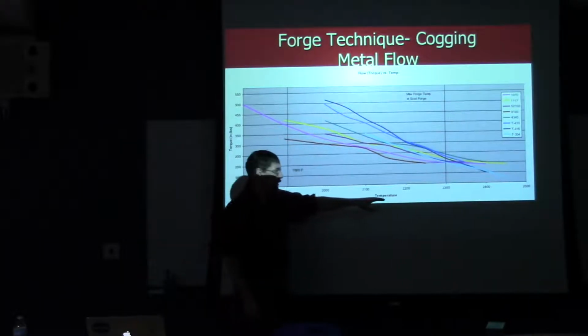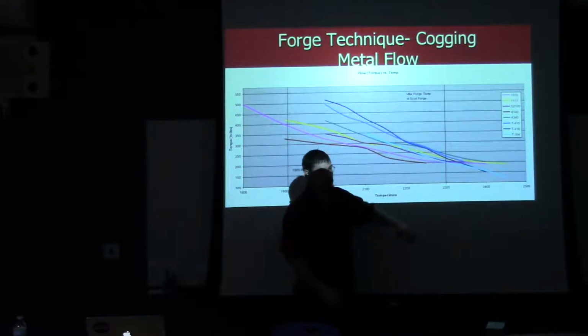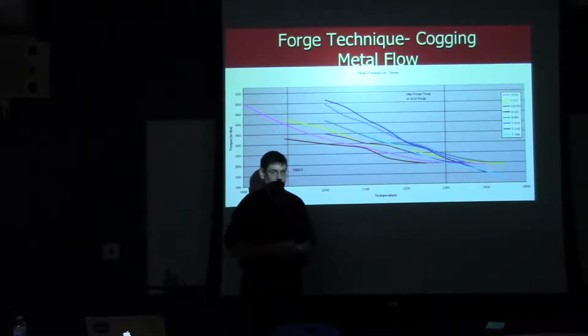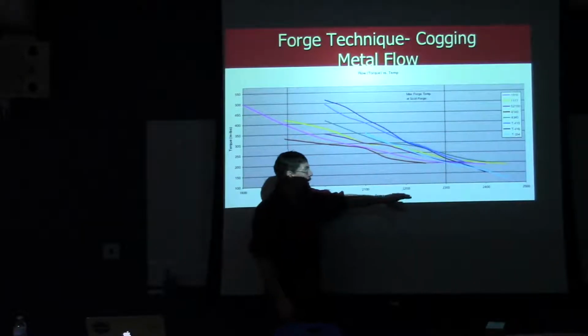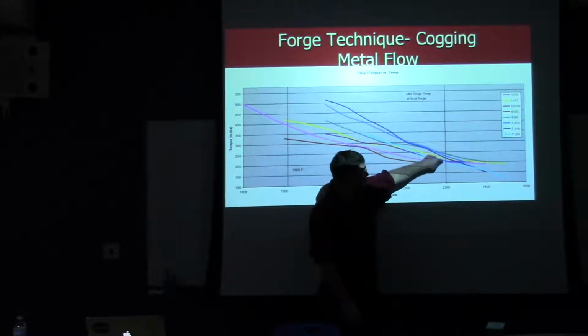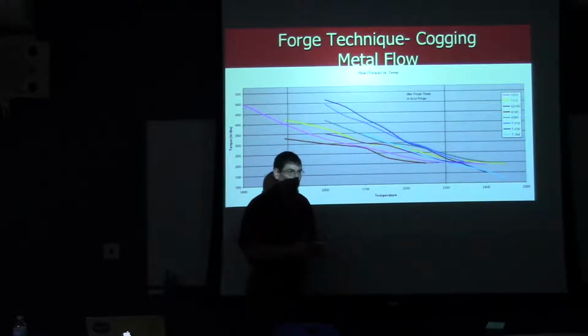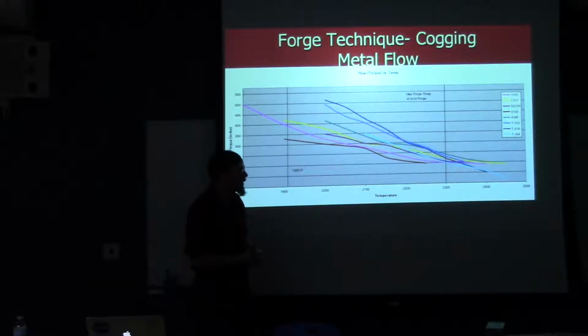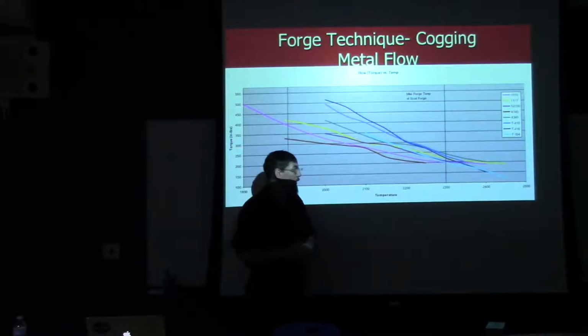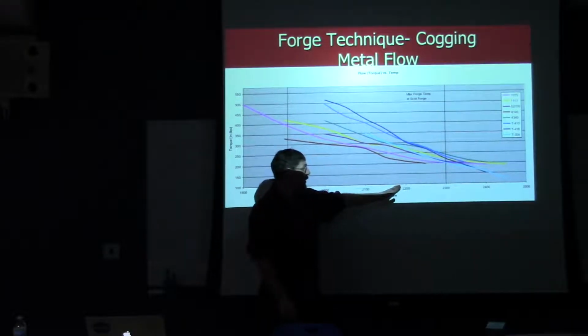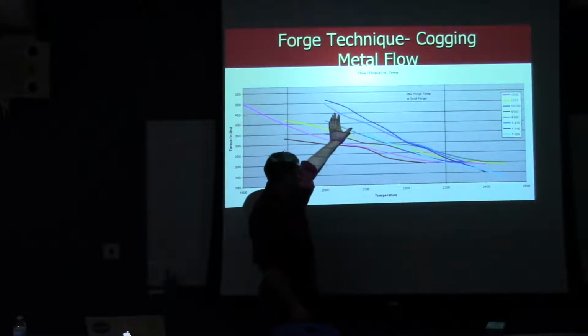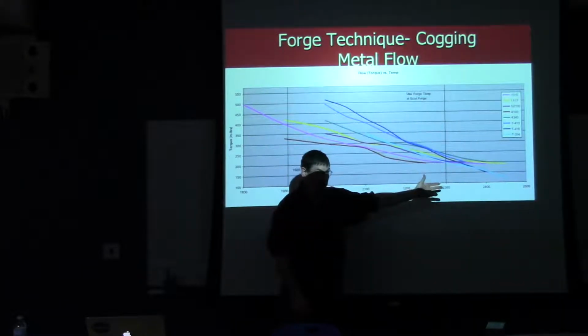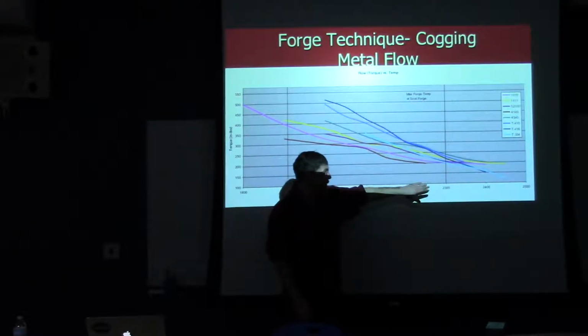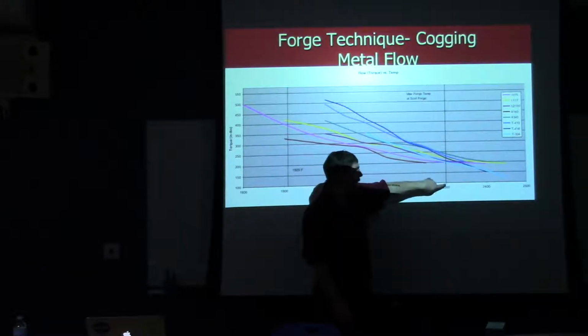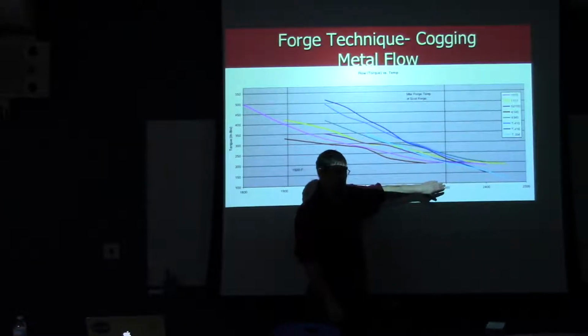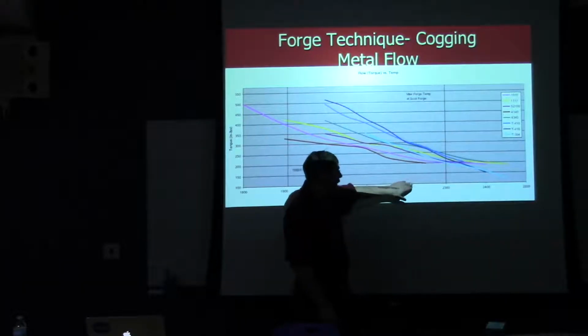Over here, 2300 degrees, this is a typical maximum forge temperature for a lot of things that we would work with. And we can see that at this temperature range, there is a spread in how much torque, or we could say flow stress, is required to move that, but they're fairly close together. As we decrease in temperature, we see that that spread is magnified substantially. So in the practical application of this is that not every grade is one that we can forge at this temperature. Some things, because of their composition, require that you start at a lower temperature.